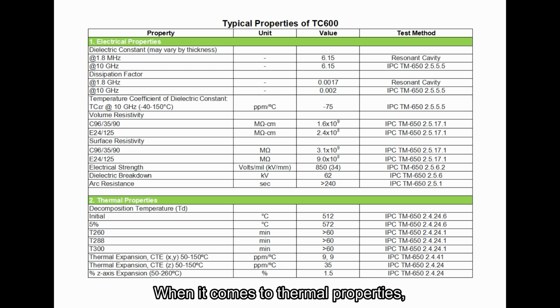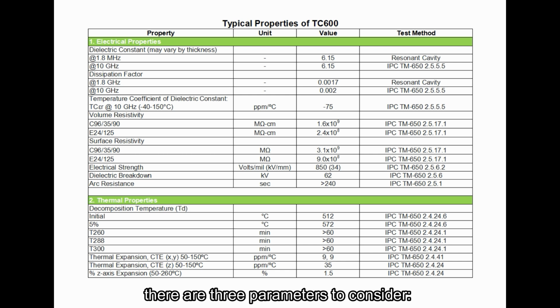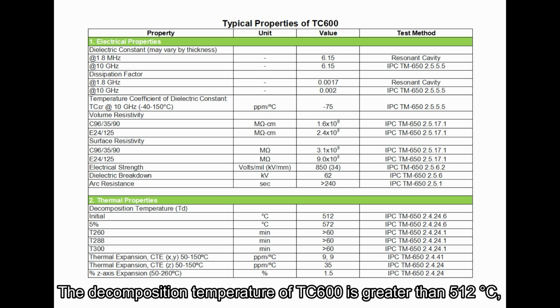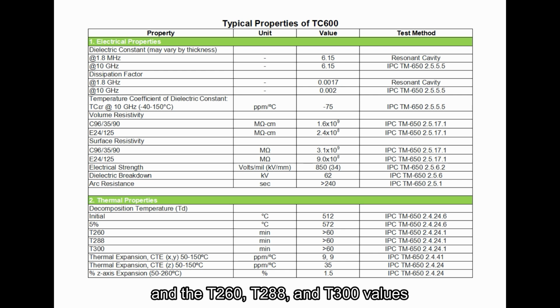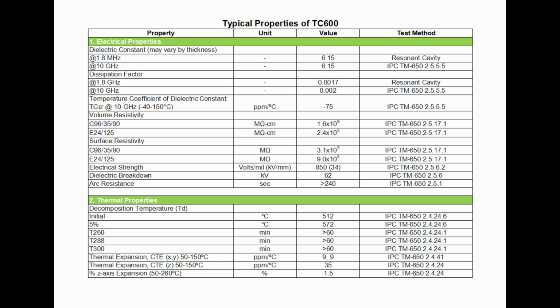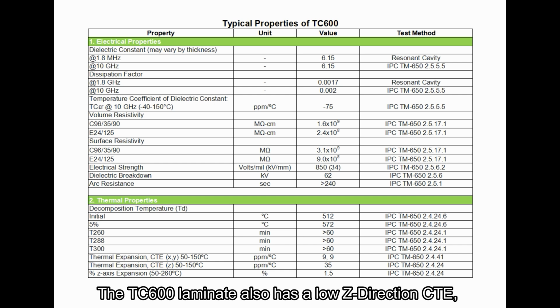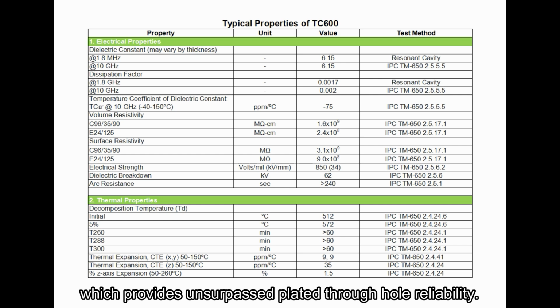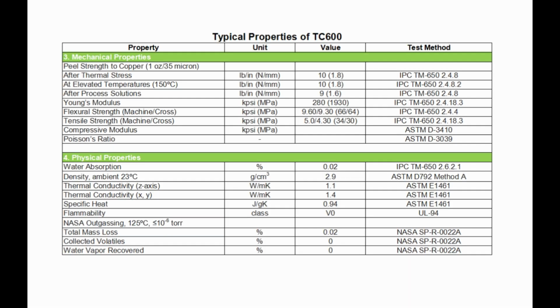When it comes to thermal properties, there are three parameters to consider: Td, time to delamination, and CTE. The decomposition temperature of TC600 is greater than 512 degrees Celsius, and the T260, T288, and T300 values are all greater than 60 minutes. The TC600 laminate also has a low Z-direction CTE, which provides unsurpassed plated through-hole reliability.